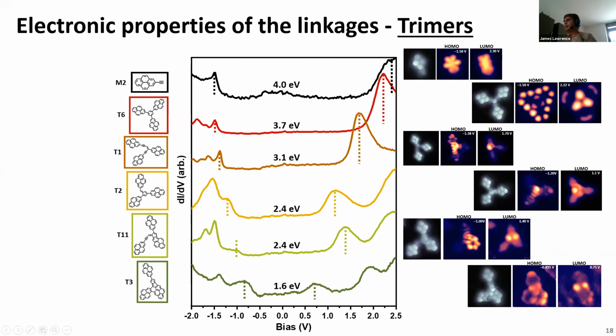And as you can see there, if you take constant height dI/dV images, well, actually this is constant current, but most of the rest are constant height, you can really see where these states are localized on the molecules, in particular how they concentrate in these new linkages that are formed. So if we try to use some kind of hand-wavy chemistry style explanations of these trends, we can rationalize why they might be happening.